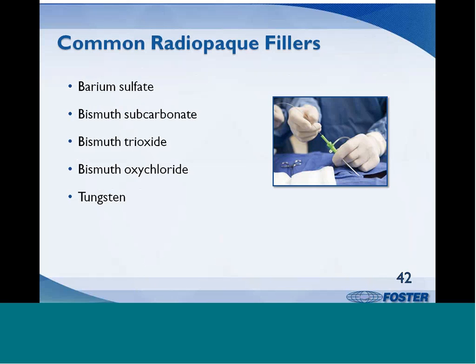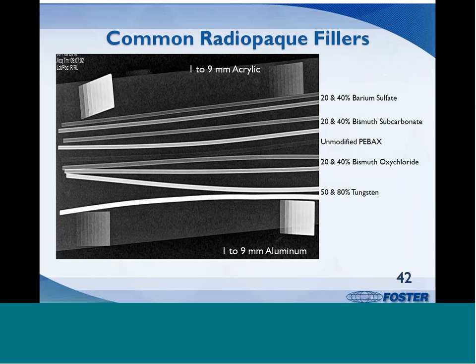The key fillers are barium, bismuth, and tungsten-based. This X-ray shows the effect of loading on the different types of radiopaque fillers. Starting from the top, you can see 20 and 40% barium sulfate and 20 and 40% bismuth subcarbonate. The middle tube that you can barely see is the unmodified neat resin. Continuing with 20 and 40% bismuth oxychloride and 50 and 80% tungsten.